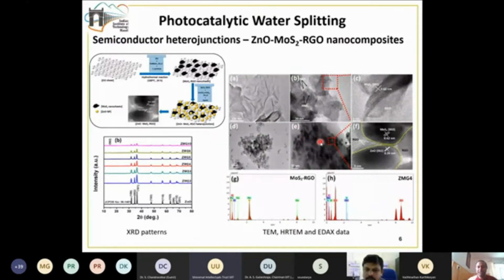And in the HRTEM image, we can clearly see the interface between them. That's why we are calling this material a heterojunction, because there is reduced graphene oxide, and there is also this MoS2, and there is also the zinc oxide, and all these three are touching each other, and they should ideally be touching each other in order for this electron transfer to take place during the photocatalytic process. So we found a heterojunction in this case. And this is the EDAX data, which shows the presence of all the constituent elements.